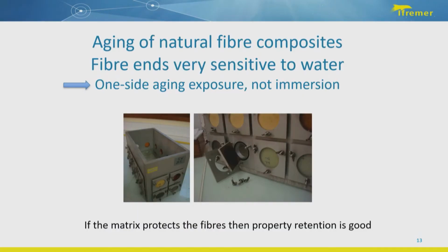So what we are doing in the laboratory is to use this kind of water tank. You have two pictures here. We put natural seawater in the tank, and you can see that there are different holes in the side of the tank, and we can seal the samples on the holes, which means that the water is only in contact with one side of the samples. The result for this kind of test is that if the matrix protects the fiber, if it is well around it, then the property retention is really good, and there is no problem with this kind of material. And this has been verified with several examples.